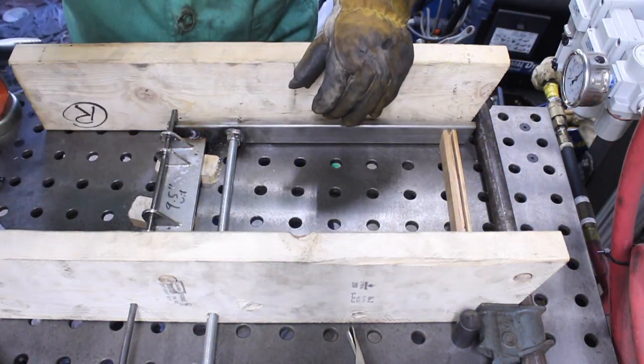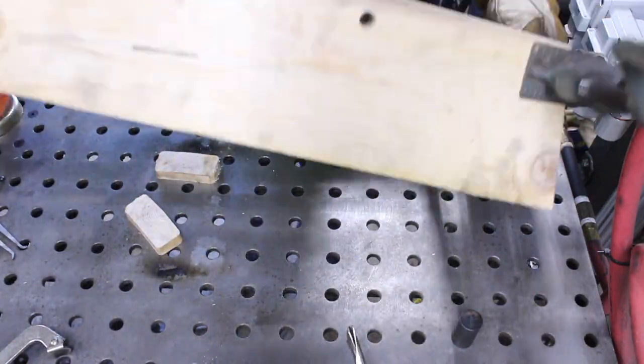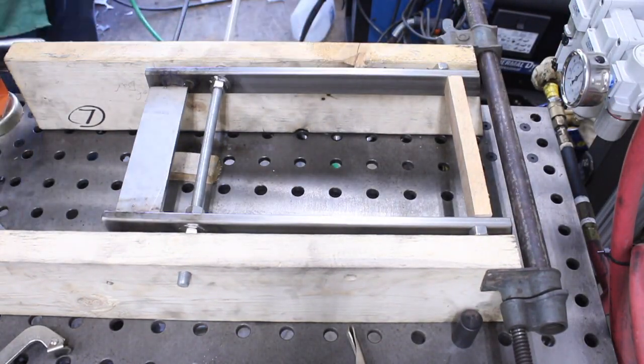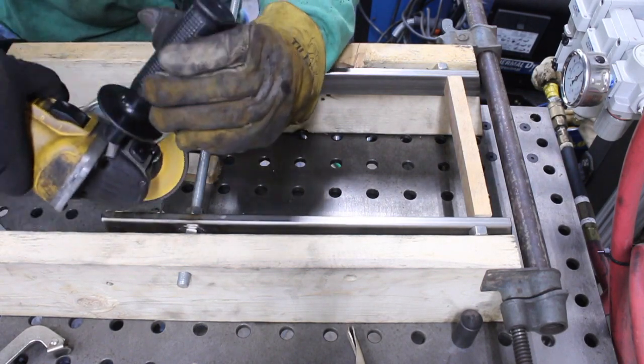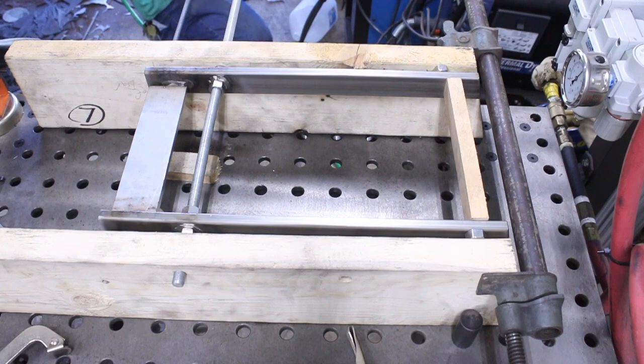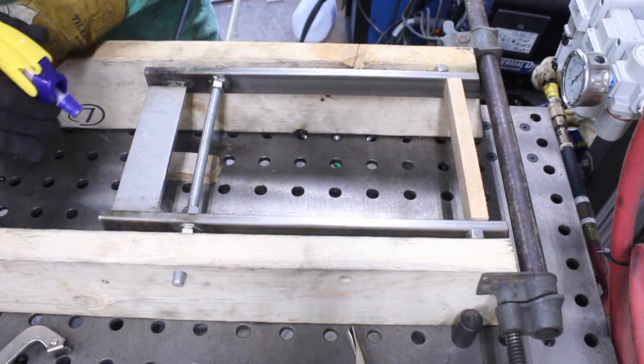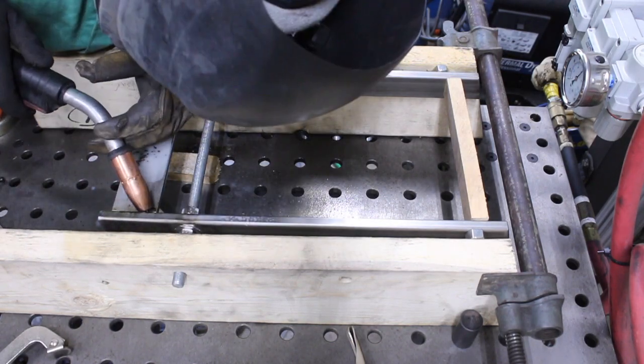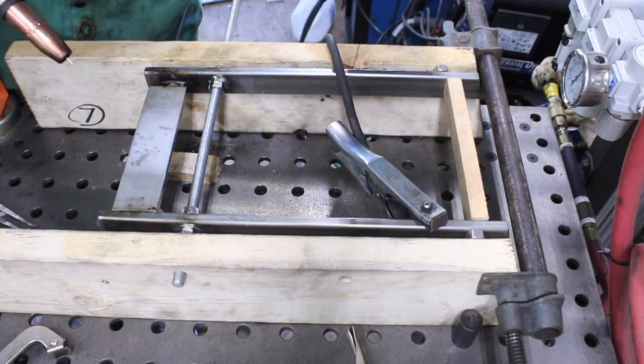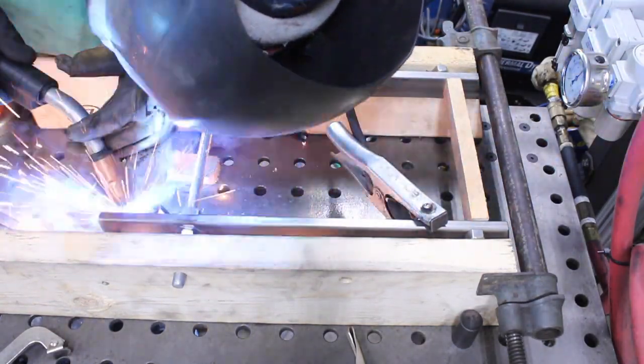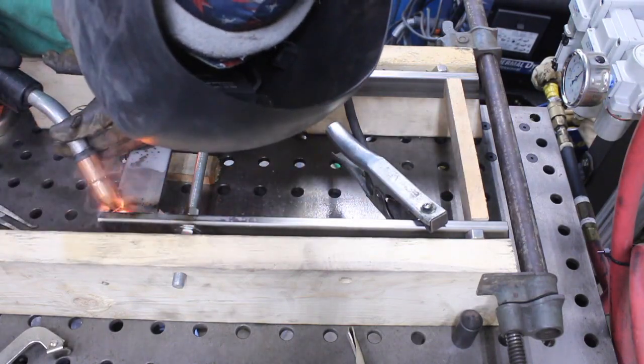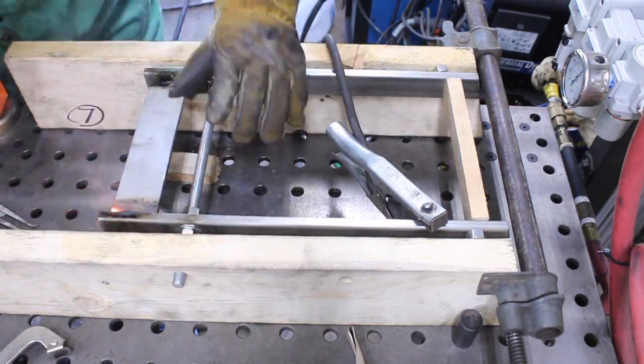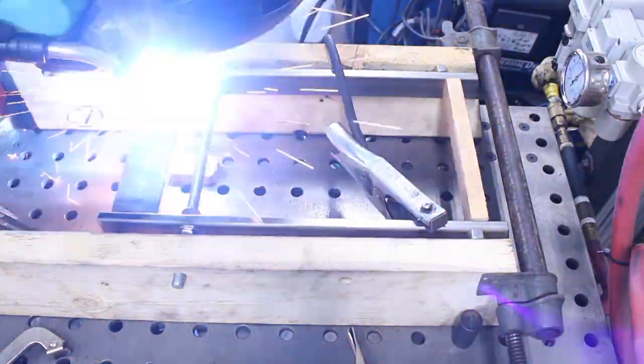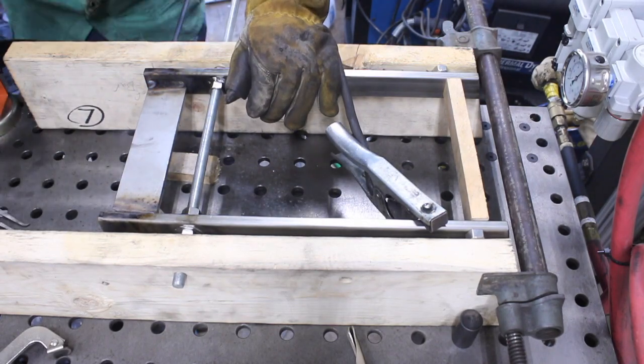One thing you'll see me do a lot is I'll use anti-spatter spray to mitigate spatter and to mitigate iron contamination, and I will use a chipping hammer that is a stainless chipping hammer, again because of either iron smear contamination or damaging that chromium oxide passive protective layer that stainless steel grows. But the most important thing about an anti-spatter spray is it has to be carbon-free, because otherwise you're just pouring more carbon into that weld and to the weld joints, and in effect it becomes a contaminant.